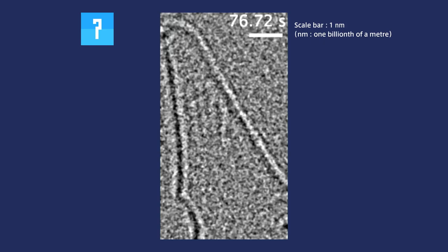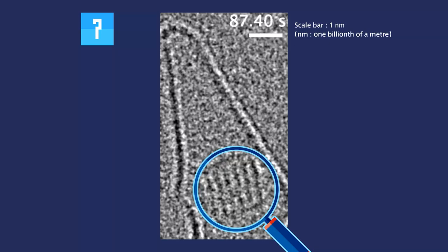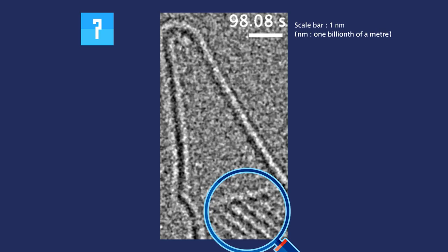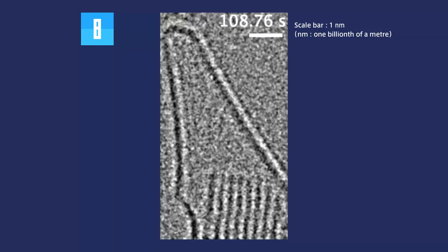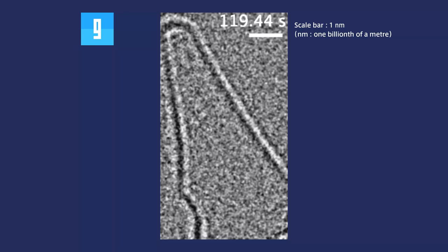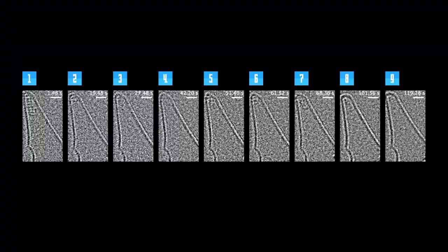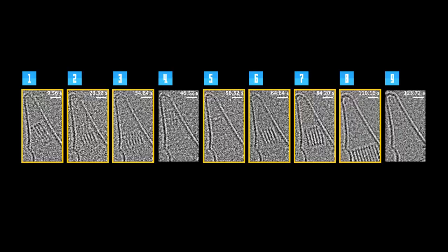Once formed, the crystal's nuclei grow larger while moving toward the wider side of the conical nanotube. These crystal nuclei appear nine times successively, creating the exact same size every time. However, in the growth process, after the crystal leaves the carbon nanotube, we find no regularity in the size of the crystal. This is considered to be the same as the irregularity of the size of crystals that normally grow in water.